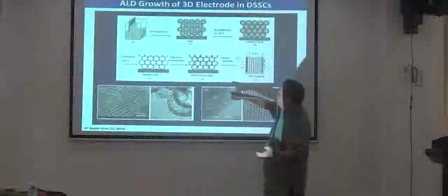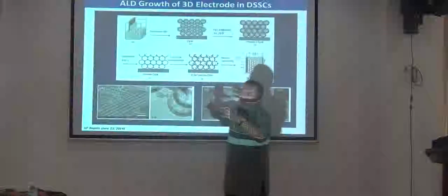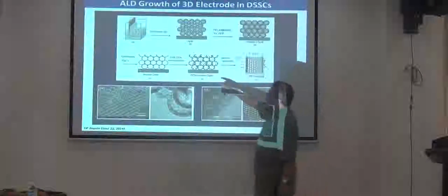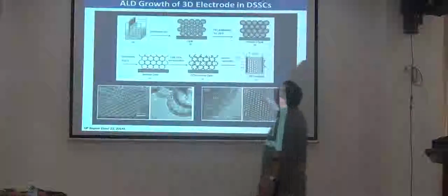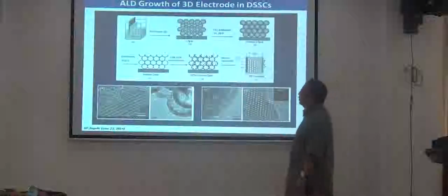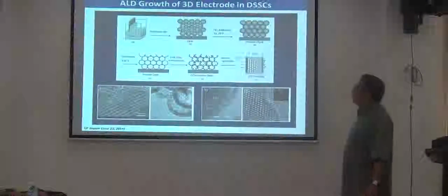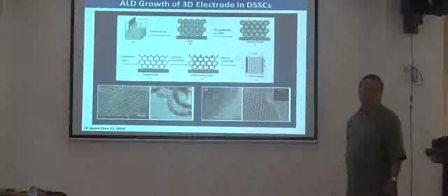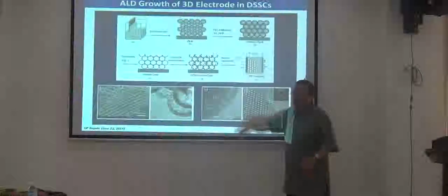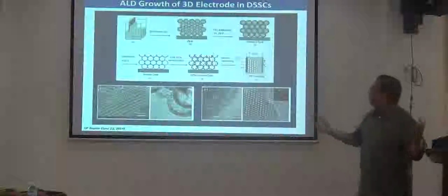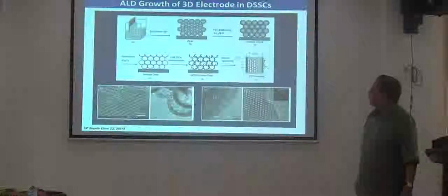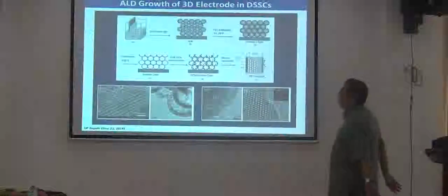So once you calcinate them, you get rid of the polystyrene spheres inside, and what you're left with is a structure consisting of this TiO2 in this particular pattern. And then you can do surface chemistry to coat these TiO2 structures with, say, quantum dots like cadmium sulfide quantum dots, and you can incorporate that electrode into whatever application you like. Like illustrated here is a dye-sensitized solar cell, but you can also use this for capacitors.